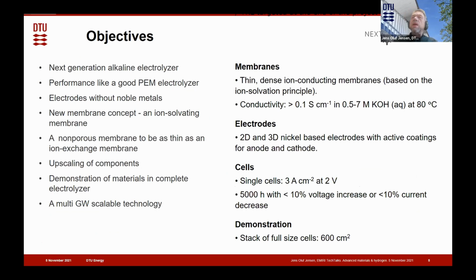So the objective is to make such an electrolyzer and demonstrate PEM-like performance without the use of noble metals. That's one of the nice things with the alkaline system. We do not depend on noble metals for a catalyst. We have lots of nickel-based materials that are actually very active in the alkaline environment. So we'll develop membranes like that, and we will develop better electrodes, and then we will demonstrate everything in the electrolyzer after some upscaling, as I already mentioned. And that should be a fully scalable technology that can go to the multi-gigawatt or even terawatt scale eventually with this technology.